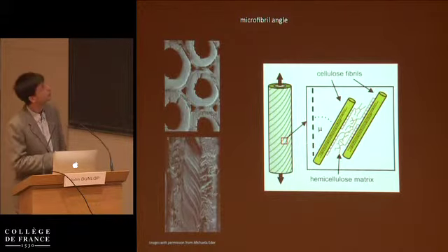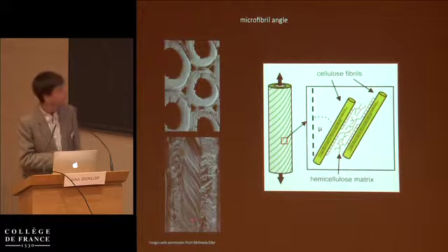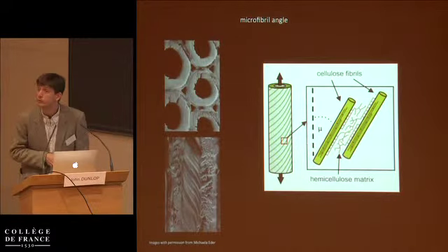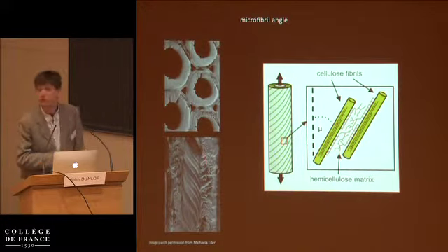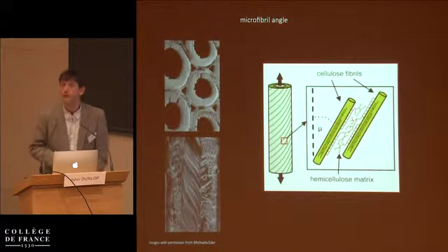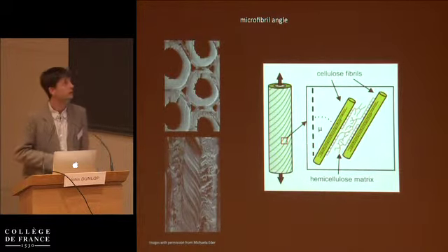And if you look, say, in a cross-section in the SEM, in some special cases, you can also see the consequences during drying of this microfibril angle, where you can see, if you cut carefully, this splitting that's occurring here during the drying in the SEM, which gives you an indication of the microfibril angle. Another way of measuring it, of course, is to use X-ray diffraction, methods that I'll show you a little bit later.